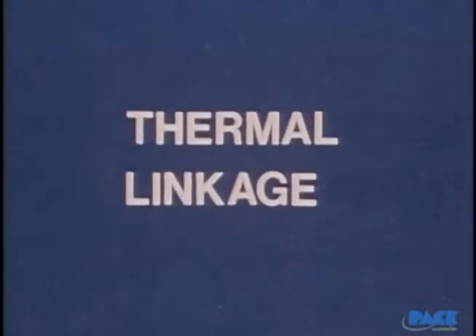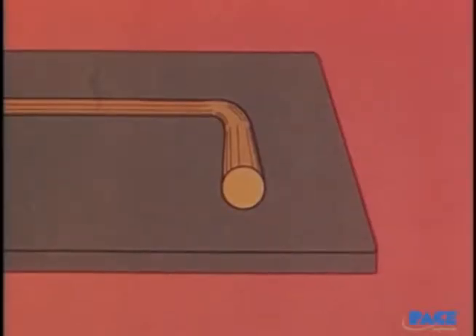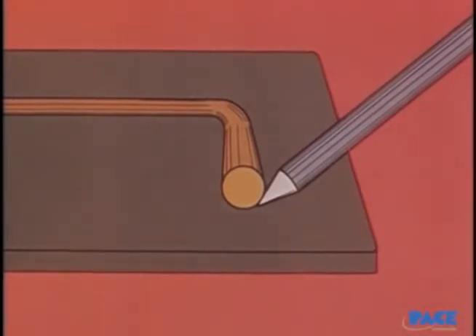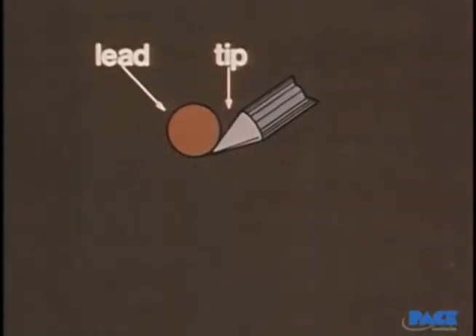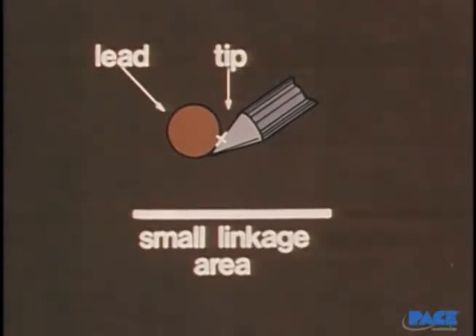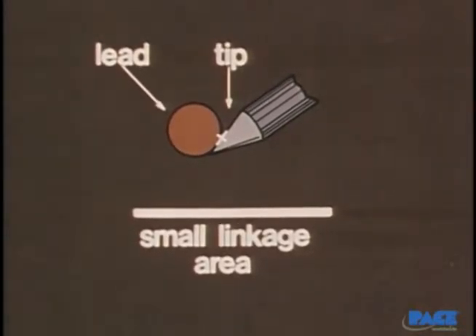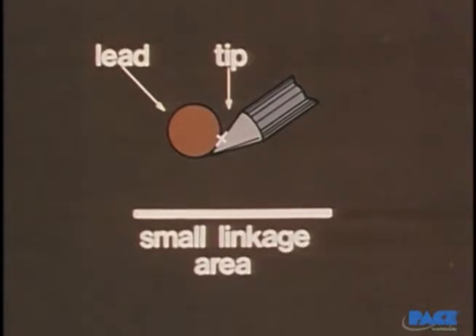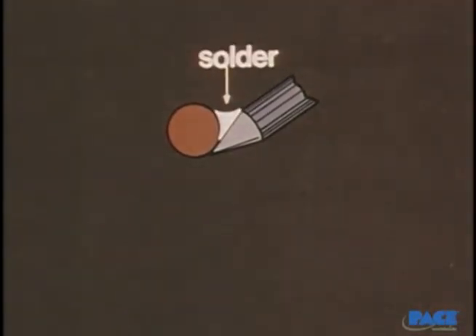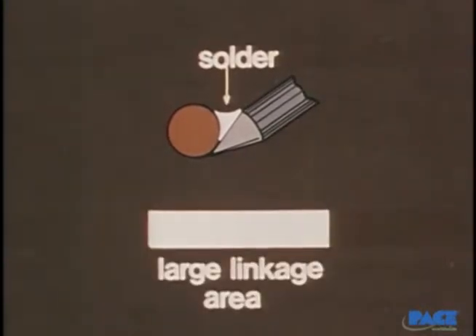After surface condition, there's a third factor to consider: thermal linkage, the area of contact between the iron tip and the work. Let's look at the situation in cross-section with the iron tip touching a round lead. The actual contact occurs only at this point, so the linkage area is very small, not much more than a straight line along the lead. We can improve things a great deal by putting a small amount of solder right here. Now the linkage area looks more like this, and heat flow will be much faster from the iron tip.